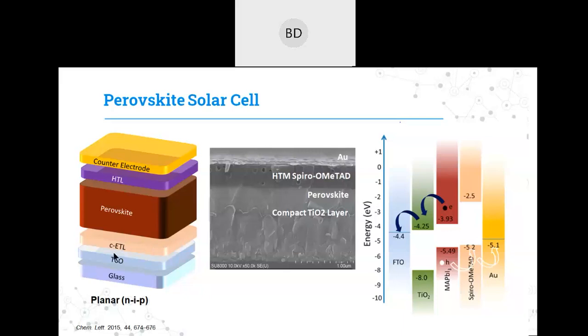Then over the electron transport materials, we have a perovskite absorber layer, which will be generating the electron-hole pairs. Then to extract the holes, we have hole transporting materials, which are mostly organic materials like spiro-OMeTAD or PTAA. But if you are talking about an inorganic hole transporting material, then molybdenum oxide is nowadays a good option. Then, to have a counter electrode, we generally use gold or silver or copper.